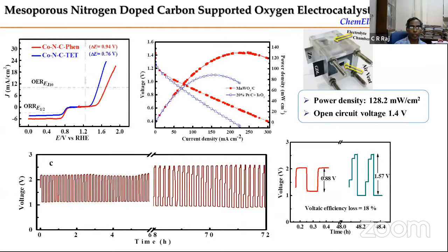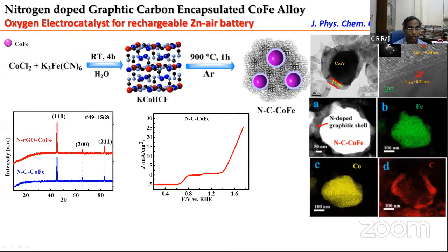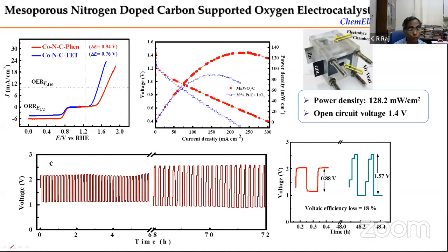Now I come here, right? In the previous case, what I said is that it was oxygen reduction active. That was inactive towards the oxygen evolution reaction. Here I have a catalyst that is active towards both. So this is your oxygen reduction. That implies, for those who are not familiar, leave it. And here you have your oxygen evolution. The same catalyst catalyzes both reactions, oxygen reduction and oxygen evolution.